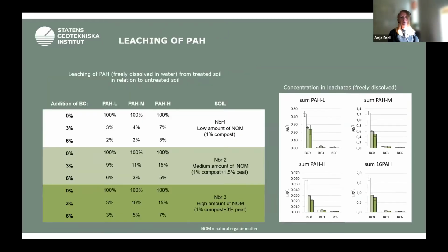So if we move on to the results of the leaching experiments, here you have the results of the leaching of PAHs, and the concentration of all the 16 PAHs that we investigated radically decreased. So you can see here a very sharp trend with more biochar in the soil. And if we look at the table here, here is the leaching of the PAHs from the treated soil in relation to the untreated soil. So if we have no additional biochar, 100% is leaching out. But already after an additional 3%, the leaching is reduced down to 3, 4, or 7%.